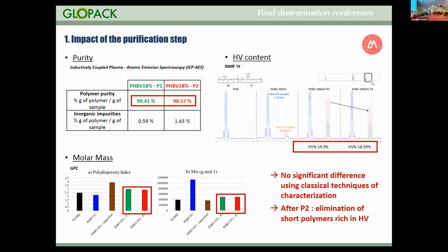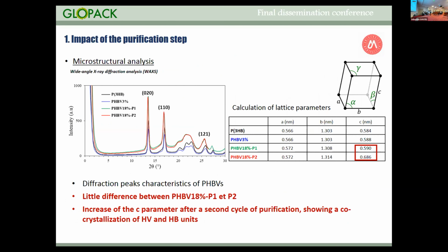And also what was very interesting is that the HV content was a little bit decreased, and this was attributed to the elimination of short polymers rich in HV. A second important characteristic was deduced from wide-angle X-ray analysis. This kind of analysis allows to characterize the crystalline structure very precisely of materials, and also to get the lattice parameters, so the dimensions of the very small lattice that is constituting the crystals.